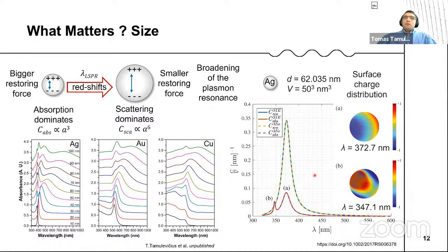And here is a bit more sophisticated numerical example I borrowed from some publication, where we have a silver sphere of diameter 62 nanometers and some volume here. You can see this blue or truncated yellow line, which represents scattering by this sphere. And you have absorption here at the bottom with the two peaks. Those two peaks are shown here as the surface charge distributions. At this peak A, we have a dipole, and at this peak B, we have a quadrupole. That is the same thing that I was showing at the very beginning when I started speaking about localized surface plasmons.